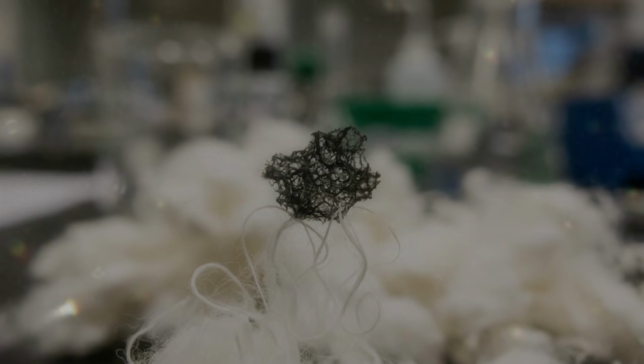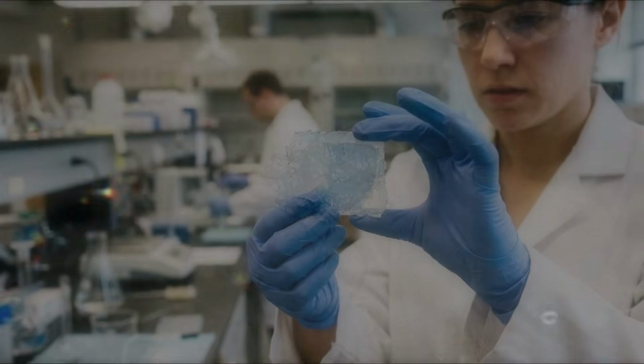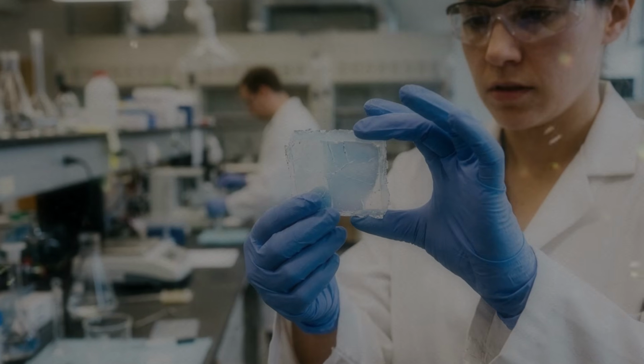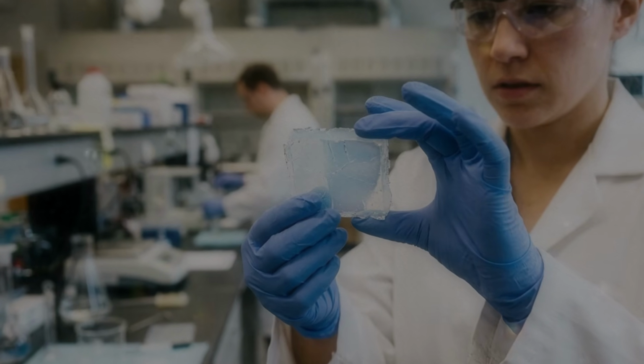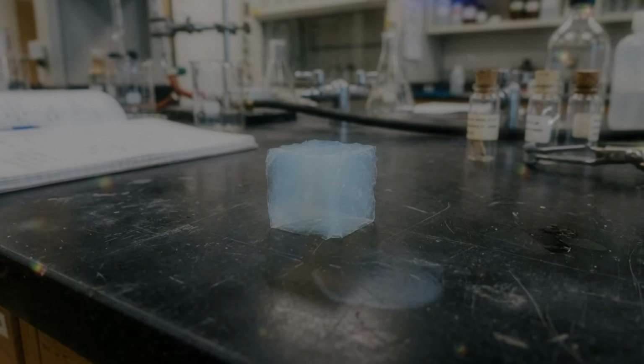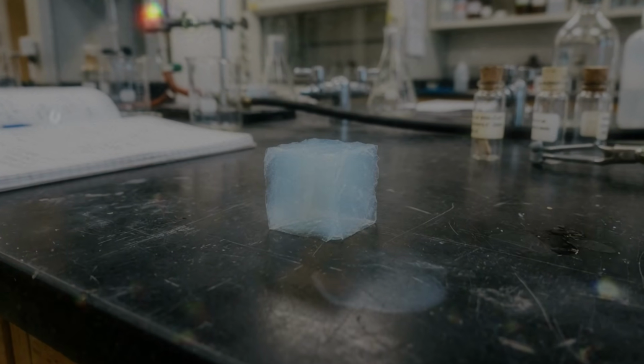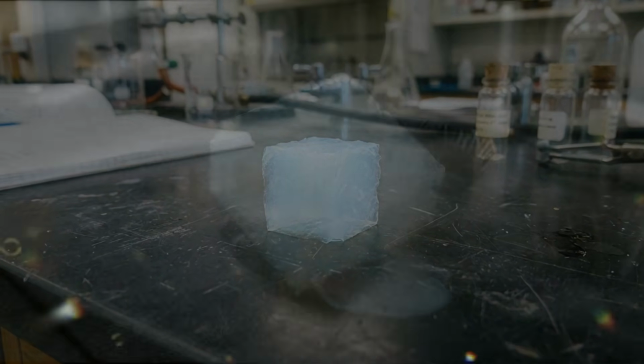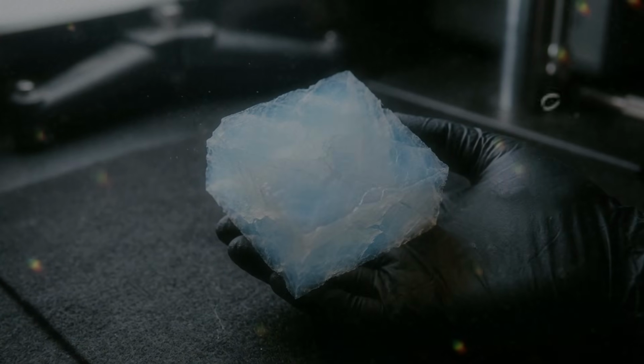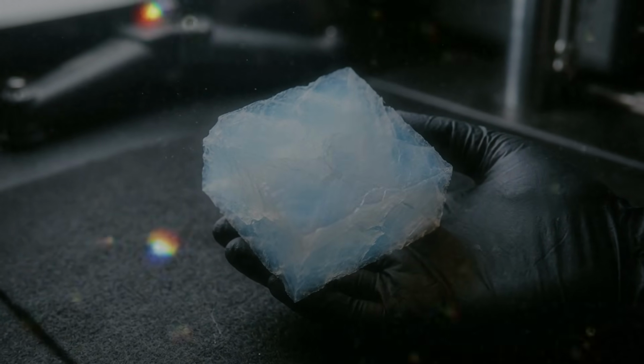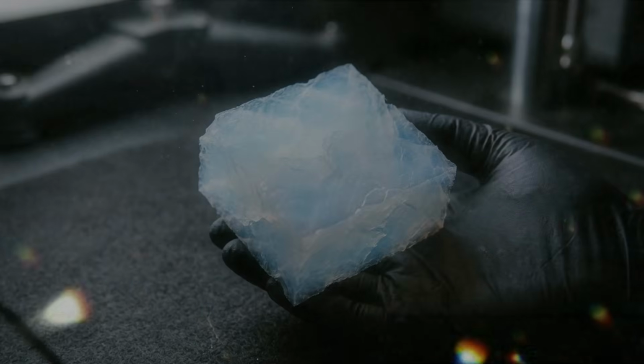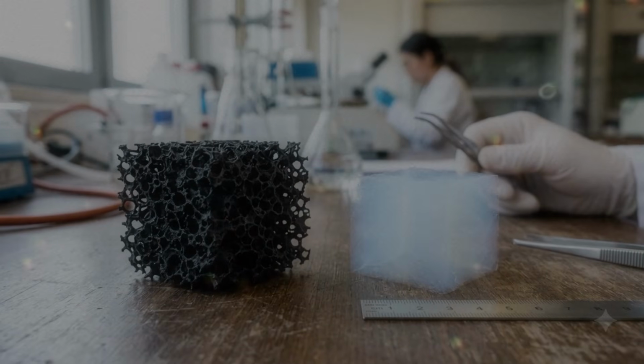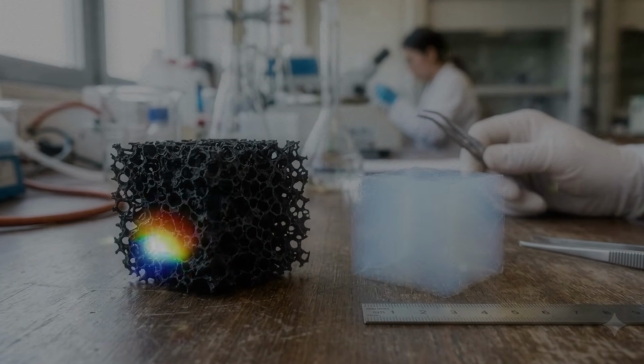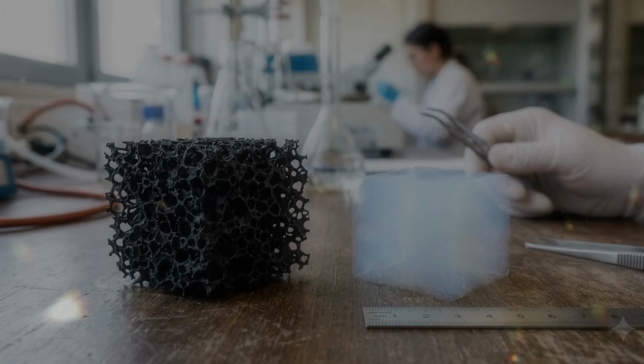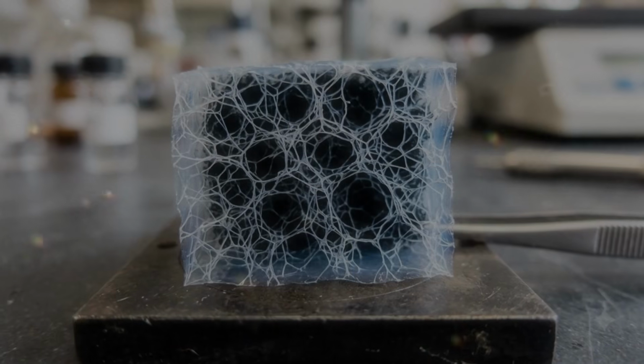Foam usually contains bubbles separated by thicker walls. Some foams have closed cells, while others have open passages. Their pores are often much larger than those in traditional aerogels. Aerogels tend to contain finer structures and much greater internal surface area. The boundary is not always perfectly clear, and researchers sometimes use terms such as aerogel, foam, sponge, and porous monolith in overlapping ways. What matters is the actual structure and method of preparation.